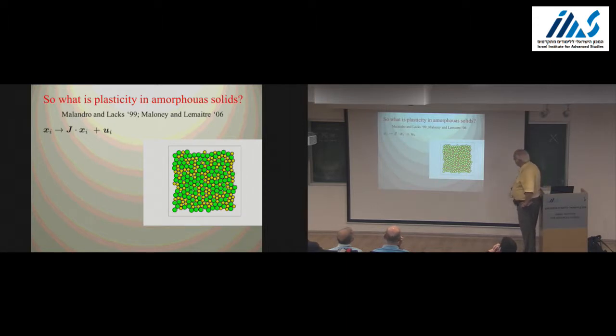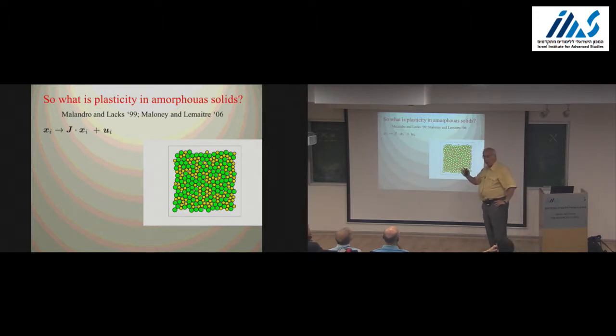And here is a typical amorphous arrangement of two types of particles. By the way, these are point particles, and the circle just shows the range of interaction. These are Lennard-Jones particles. And now I'm going to do an affine transformation. So these arrows describe how much I'm going to move these particles. So these don't move at all, and this is a linear Y dependence, and these are going to move so much. I've done it. The system was in mechanical equilibrium before. Is it in mechanical equilibrium after? Of course not, because the system is amorphous, and therefore now look at what forces have been created on every particle.